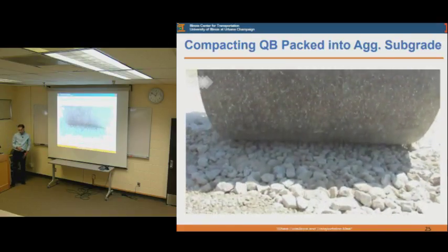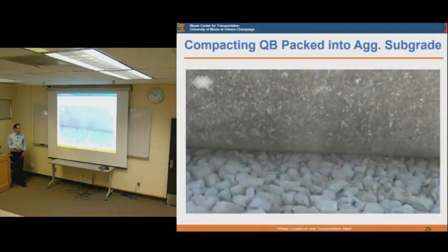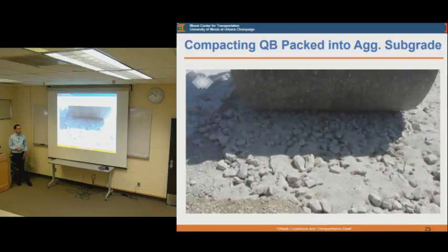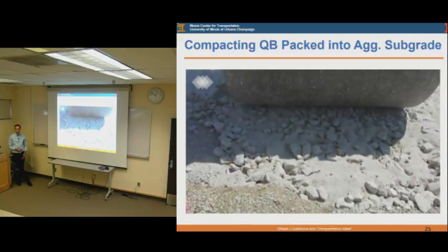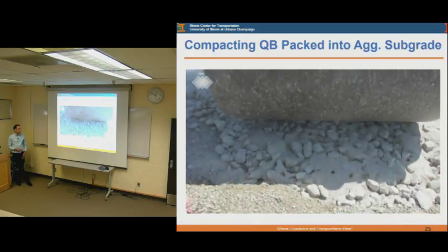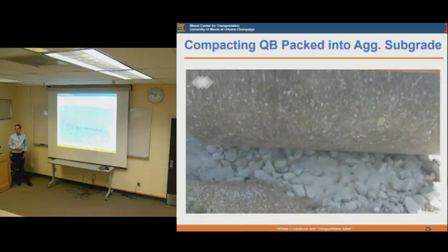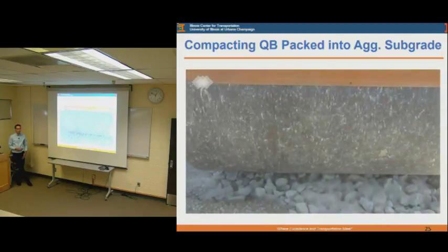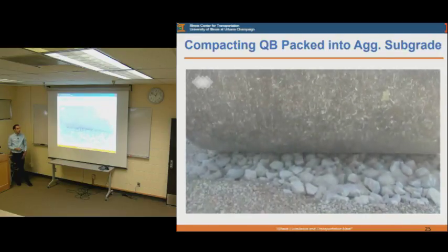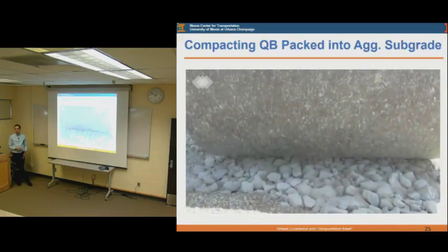One thing that we learned from this is that in order to get a successful application of the Quarry byproducts inside the large rocks, we need an incremental application of the two materials together, so we cannot just spread the whole amount at once. Another big importance is the moisture content, because this Quarry byproduct was a little bit wetter than the Quarry byproduct investigated in the lab. It had a moisture content of 3.2%, and the moisture content matters, as it inhibits the further percolation of Quarry byproduct.